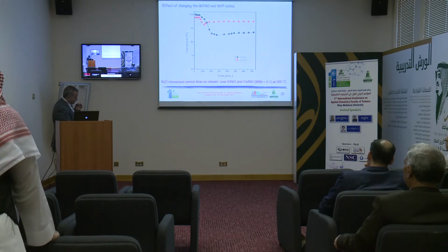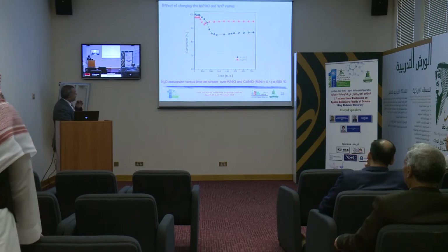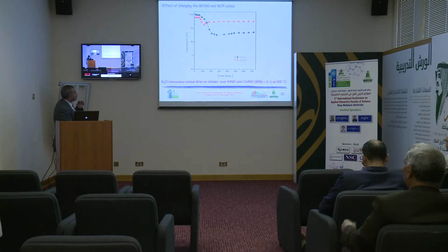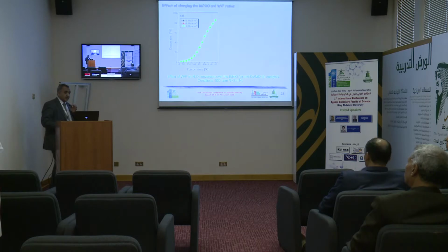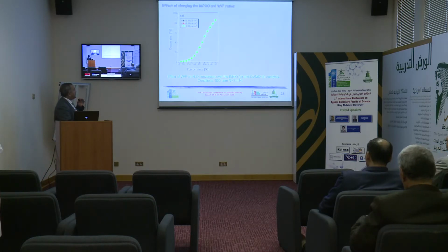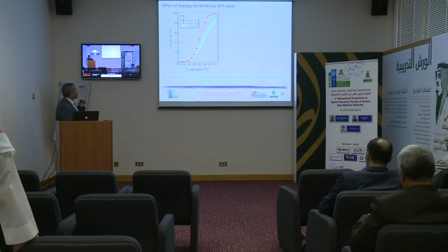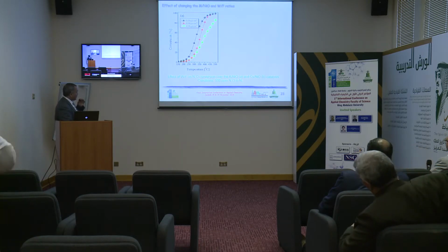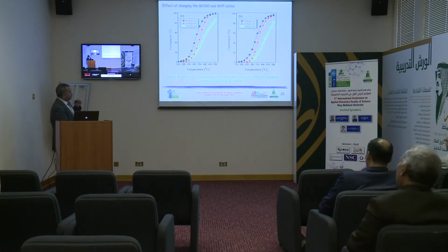Regarding cesium, durability seems to be better than that of potassium. We also examined the effect of changing the W over F. We can observe that increasing W over F shifts the reaction towards lower temperature for both higher active catalysts.